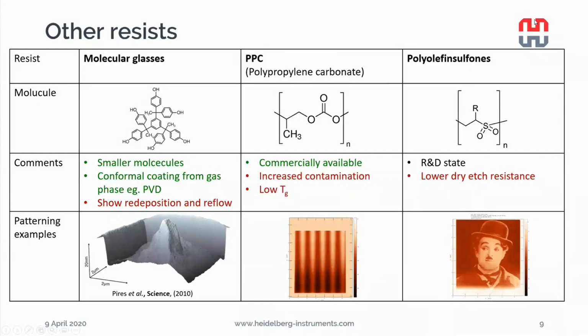Then there's polyolefin sulfones that are quite promising, still in an R&D stage, but they also show another issue, that's the lower dry etch resistance that limits your further processing. This might sound quite bad, but in the end, all of these resists have been used for patterning. They were able to successfully pattern in them with hot tips. So they all have their points to use and can be tested out if you have a special application that